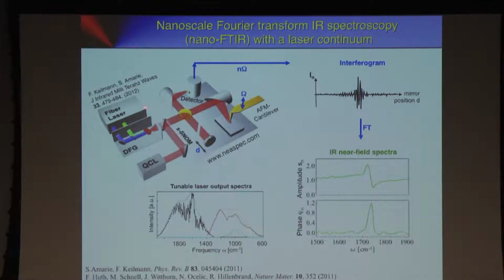The tip is fixed at the sample position, and then we move this mirror here, and we record an interferogram. And this is exactly what you do in a standard Fourier transform spectrometer. We record this interferogram here, and then we Fourier transform it, and we get the spectrum. And these are the spectra here. This is on a polymer, and we get now an amplitude and phase spectrum. And that's the difference to a standard Fourier transform spectrometer.